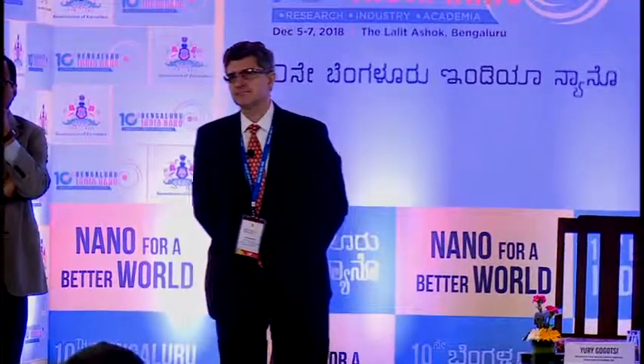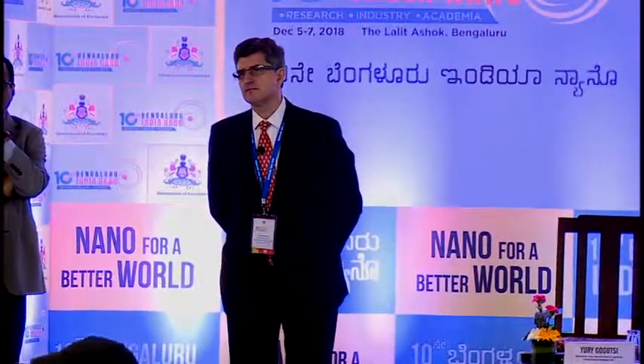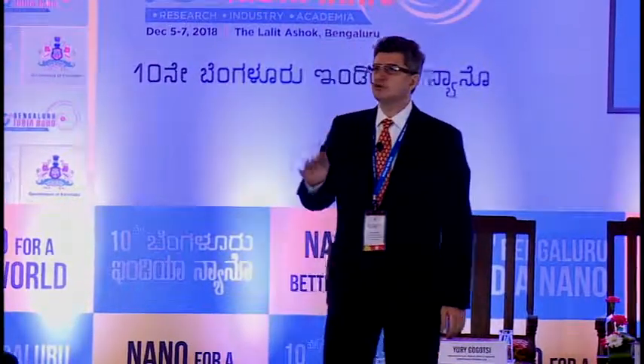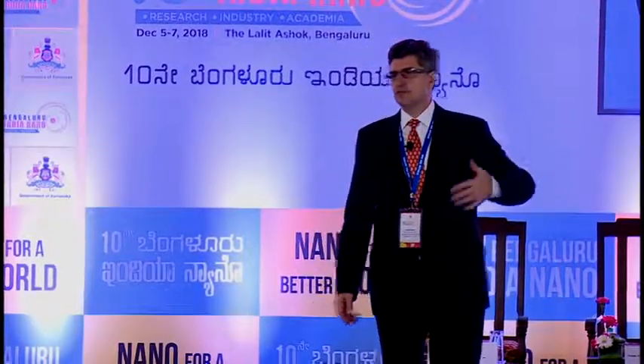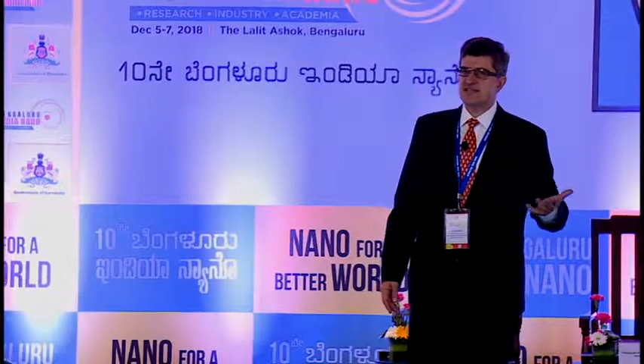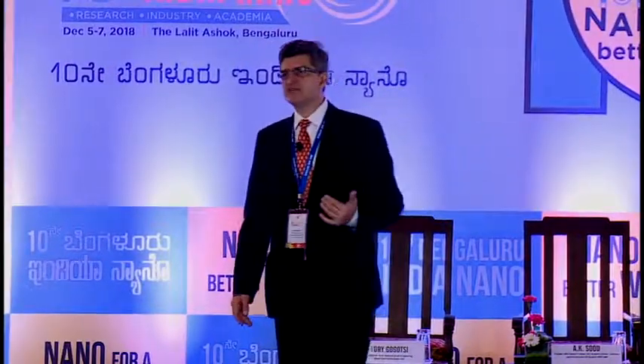One more question. What is the reason for high capacitance, because the interface is entirely different? Can you tell about that interface and how it compares? Again, most of this capacitance comes not from double layer capacitance, because the specific surface area of this material is a maximum of 600-700 square meters per gram.